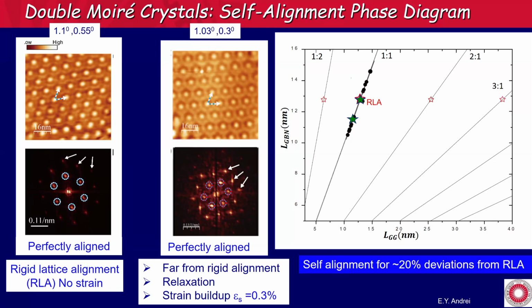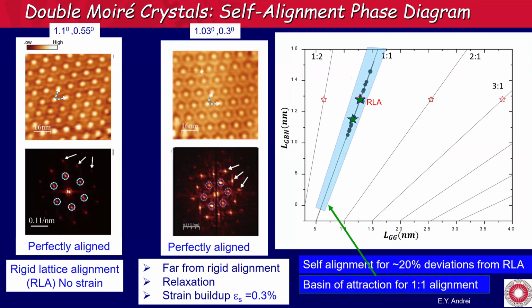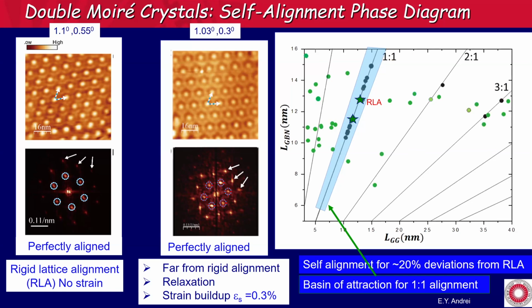How far can that go? So we find what we call a basin of attraction. There's absolutely no points around it, and we can actually understand it with a little bit of theory. But then we find many other lattices which are not aligned. They are quasi-crystals, incommensurate, they're quasi-periodic. We have a few other periodic ones. By the way, there's no basin of attraction for anything but the 1-to-1. So it really doesn't pay to align when you're 2-to-1 or 3-to-1. This is the only place where we get rigid lattice alignment.